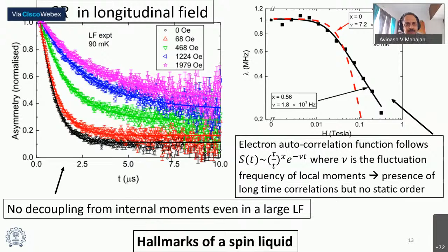Okay, the other aspect one looks at is how easily you can decouple these magnetic moments from the internal field by applying an external field. So one applies an external longitudinal field and sees how you can now, so if the external longitudinal field is strong, then of course the muon will remain polarized, okay, because of the external field. So the internal field will not be able to depolarize it. But if the moments are dynamic, then typically it is known it is hard to depolarize these muons. So here that is what is seen at the low temperature of 90 millikelvin. Even in a 2000 Oersted field, the muon polarization is not lost. You get significant muon depolarization as a function of time.